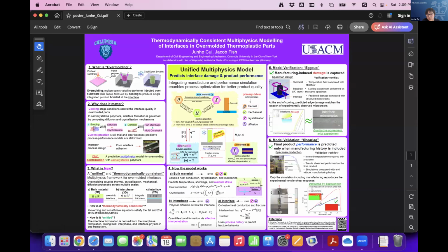And the main idea of this model is very simple. Temperature is the primary driver. In the cooling process, temperature governs the polymer diffusion, the crystallization, and part shrinkage, which together control the quality of the bonding at the interface. In the bulk material, we track the cooling and part deformation, and in the interface, we track the formation of the bonding. All this information will then be used to predict the strength and potential damage at the interface.